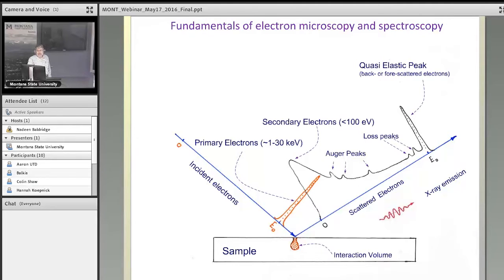Believe me, if you look at a little blip on a big background, you don't see much. But if you take a derivative of it, it shines like a Christmas tree. That's the trick in the Auger. They take derivatives of this background and they get the signal. These Auger electrons run from 0 to 2,000 eV, cover all periodic table, and they give you information from the first couple nanometers of the surface.